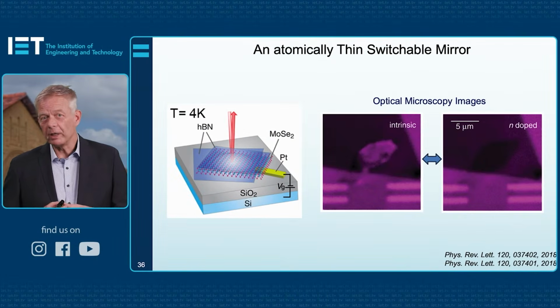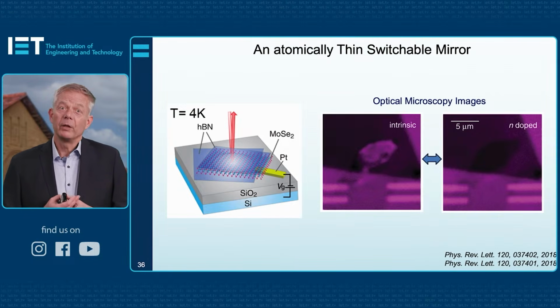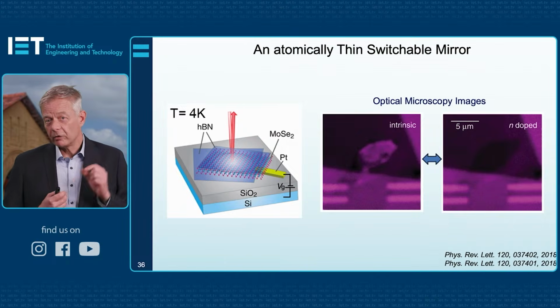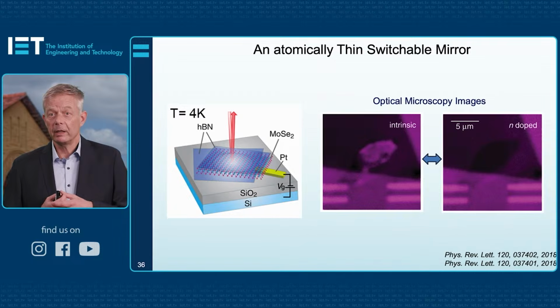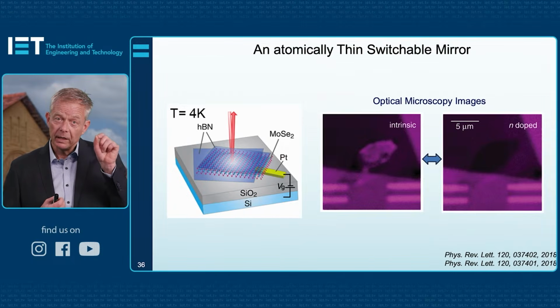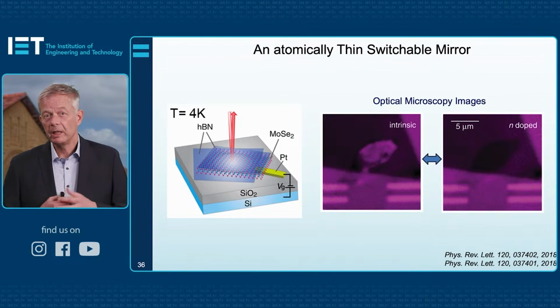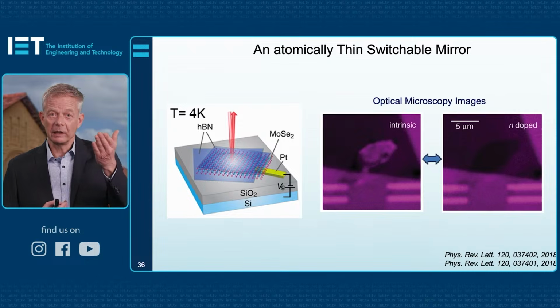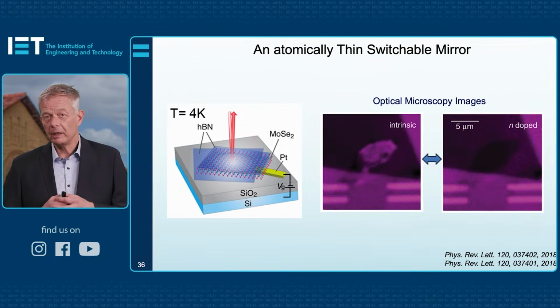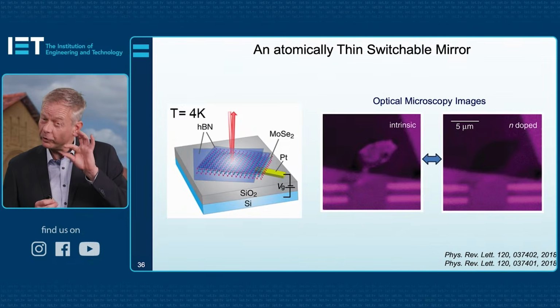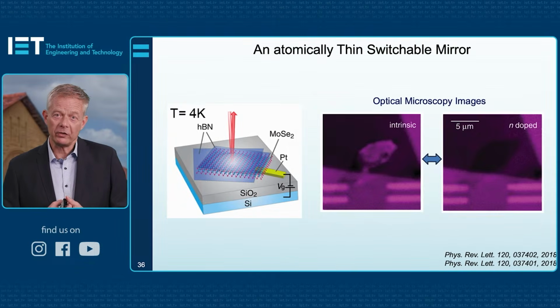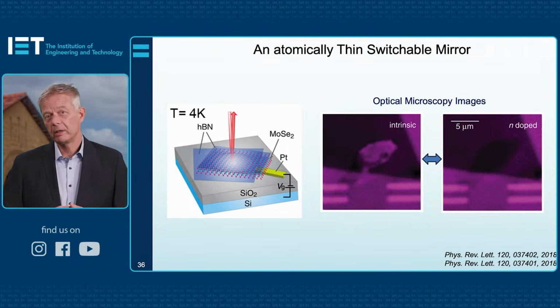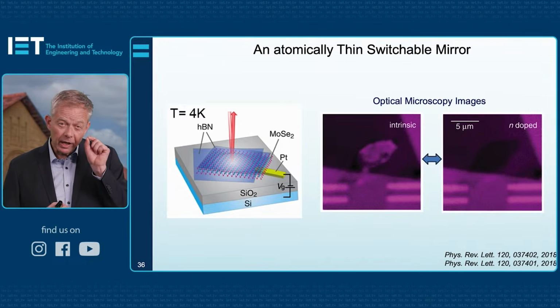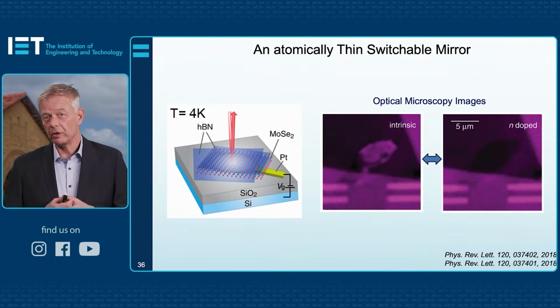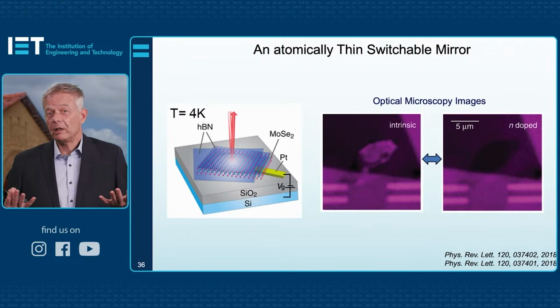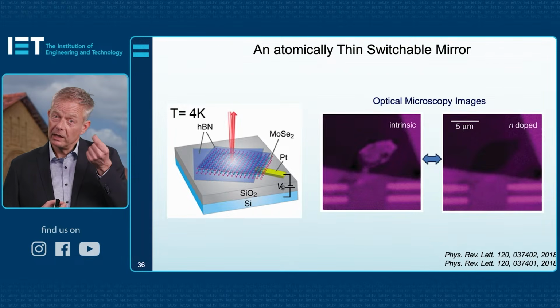This was one of the experiments that really inspired me to think about working on this topic. It's two papers that simultaneously came out from a group at Harvard and ETH that showed if I illuminate a very thin layer of atomically thin semiconductor, in this case molybdenum diselenide, at very low cryogenic temperatures, 4 Kelvin, then it turns out, as shown in the center image, this little flake, although it's atomically thin, can act as a fantastic mirror. It very efficiently reflects the light with which it's illuminated. But if you inject a little bit of current into this two-dimensional semiconductor, it turns out, as shown on the right, that the flake goes dark. And this is because the electron-hole pairs break up.